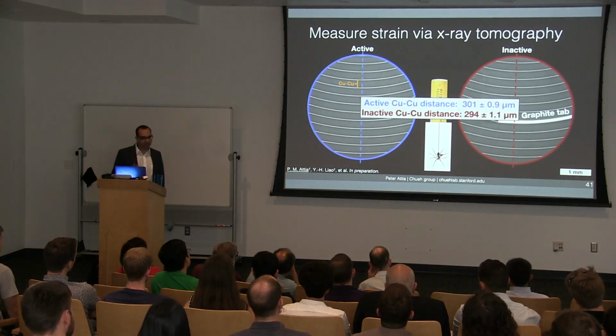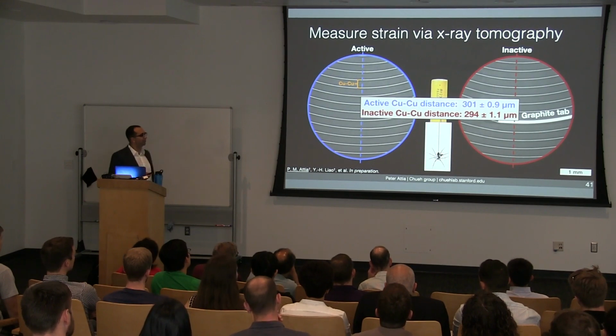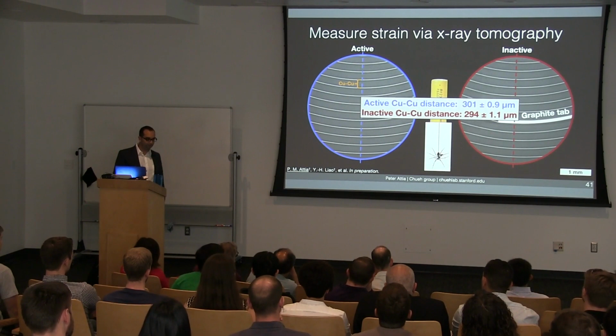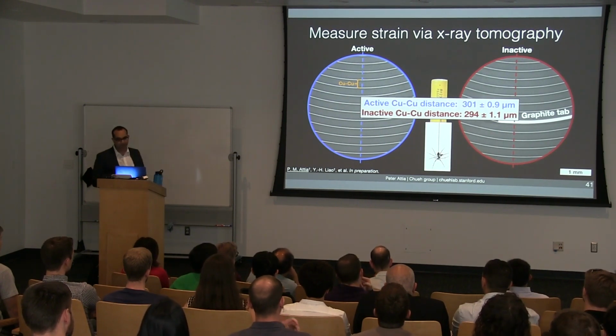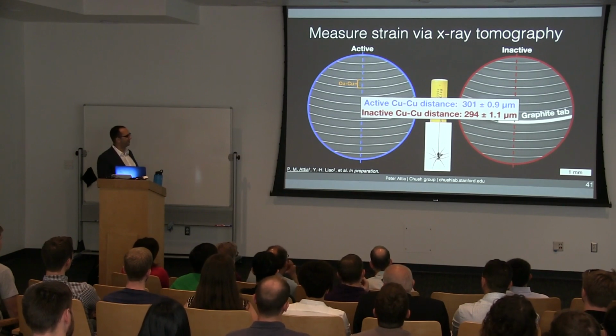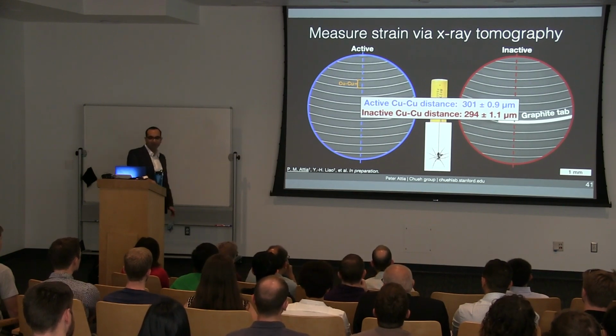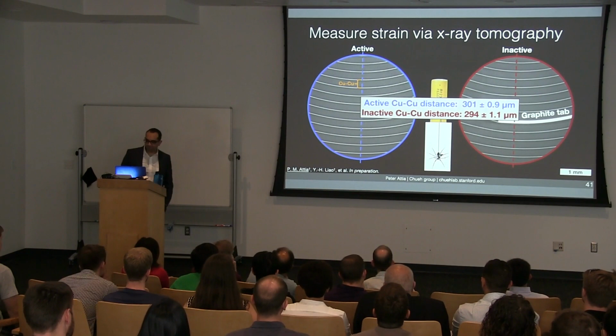If we compare the average copper-copper distance for the active and inactive regions, we get a difference of around 2%. It's pretty small, around 7 microns. It's not large, but it's just significant. Now for context, 7 microns is around the width of spider silk. So it's 10 times thinner than human hair. I mean, given the length scale of the battery, 7 microns is not that big.